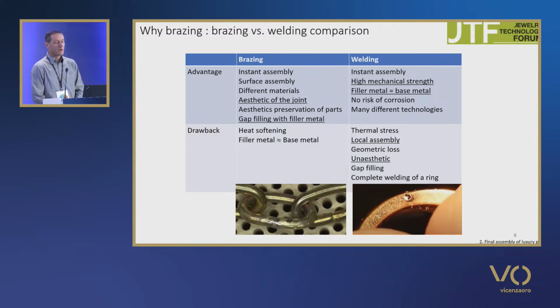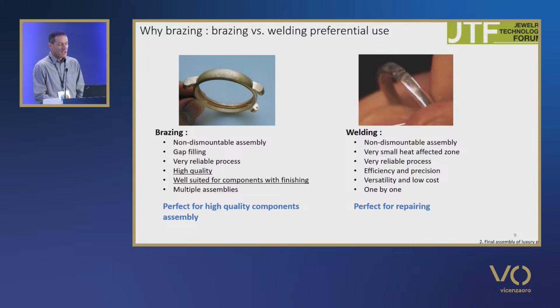Welding is very interesting for very high mechanical strengths, and it is possible to use a filler metal exactly with the same composition as the base metal. For brazing, the key point is the aesthetic of the joint. Welding has a very, very local heating, and so a small affected zone. Welding is very interesting for repairing. Brazing with the very high quality and the possibility to braze the finished part is perfect for first production.